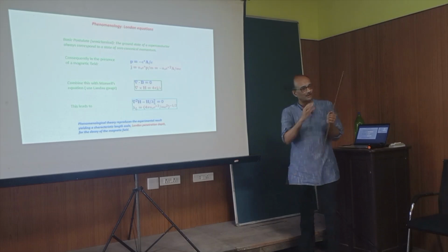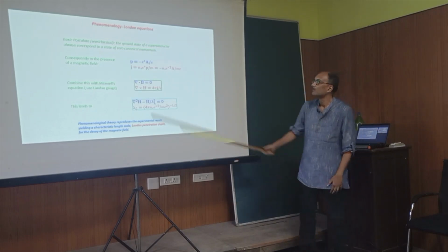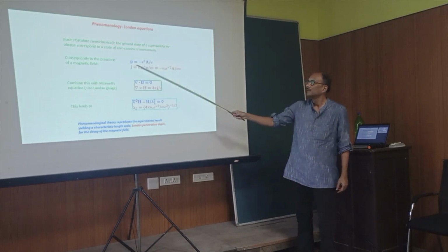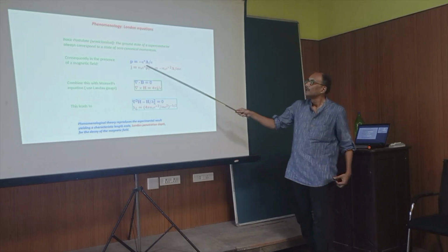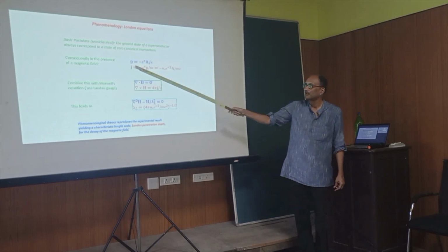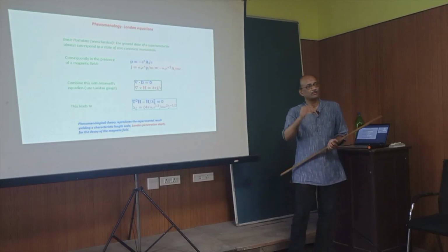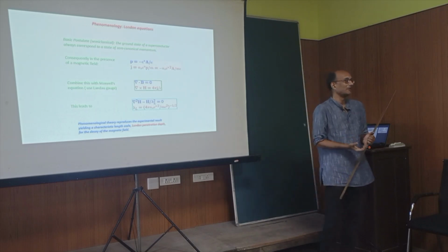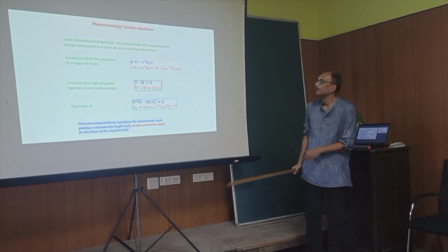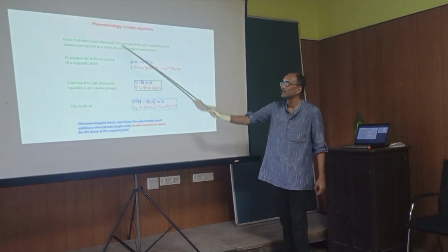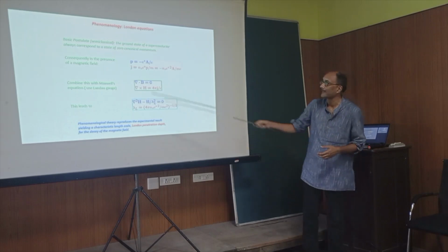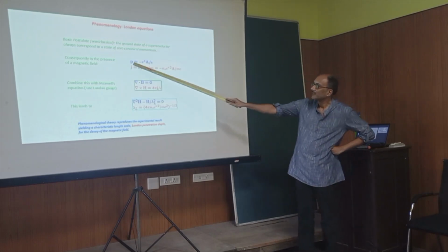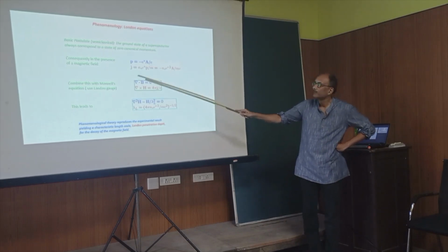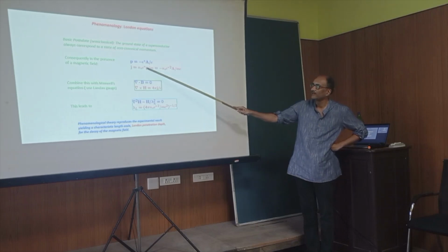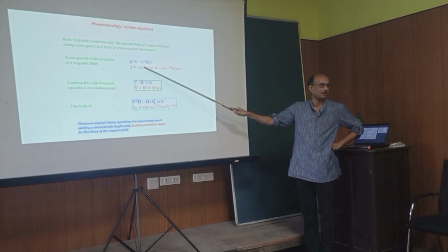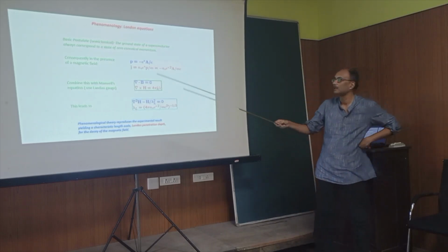It just says that the state of the electrons inside the superconductor is such that the momentum of this electron is just the applied vector potential. In other words, you know that this P is typically called the mechanical momentum, whereas when you apply a magnetic field, there is something called a canonical momentum, which is pi, which is P plus eA. So the postulate was that the ground state of the superconductor corresponds to a state of zero canonical momentum, and that tells you that P must be equal to this vector potential, from which you can get a current, because current is just the velocity, which is P over m, times the density times the charge. Okay? So that's the charge current, right? n e v, the standard stuff.